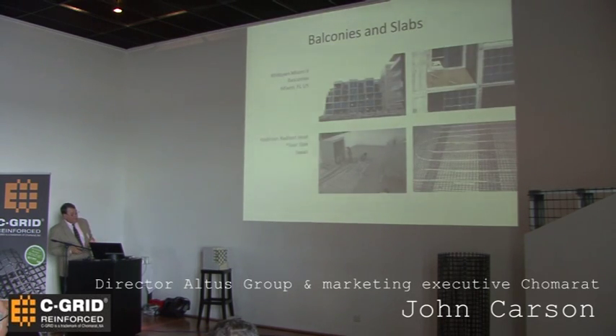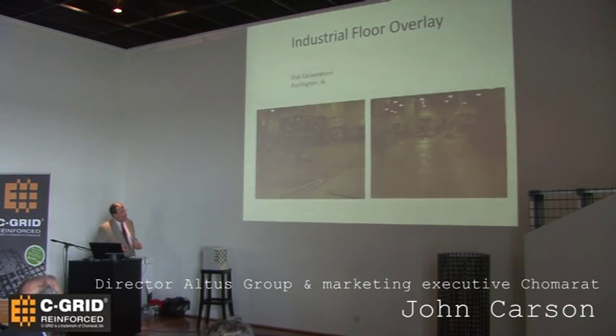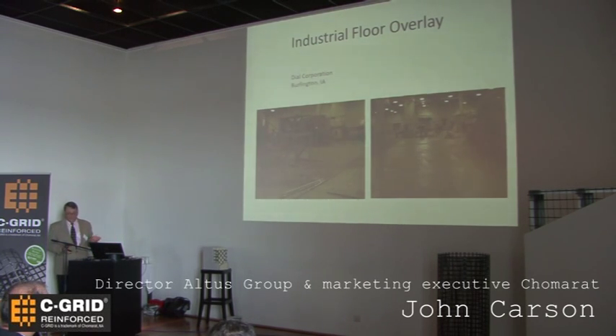Balconies and slabs, use with hydronic water systems, so common use. This happened to be a project in Japan with PEX tubing, and they wanted a crack-resistant flooring material that could be subjected to temperature. Chemical processing plants, again, aqueous moisture environments destroy the reinforcing, so use carbon fiber grid. In this case it was a repair, but why not put it in the surface original product.